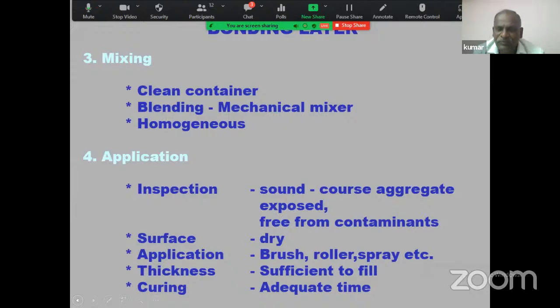Before applying the bonding layer, you have to inspect the surface and it should be free from contaminant. The surface should be dry. You can apply by either brush, roller or spray. Then thickness is to be sufficiently filled. Curing depends upon the polymer, you can give a proper curing.